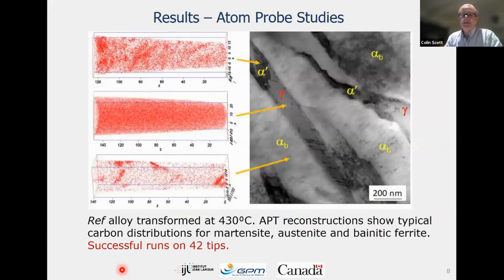We did a lot of atom probe work. So actually 42 different atom probe tips were prepared and run successfully. So here's just an example of the data that we got from the atom probe. This is quite a nice TEM image because you can see all three phases in one image. So you have bainitic ferrite, then you have retained austenite, and you have regions where that retained austenite is transformed to martensite, so alpha prime. And these are typical atom probe images from each phase.